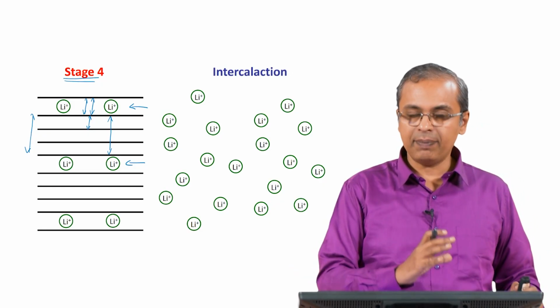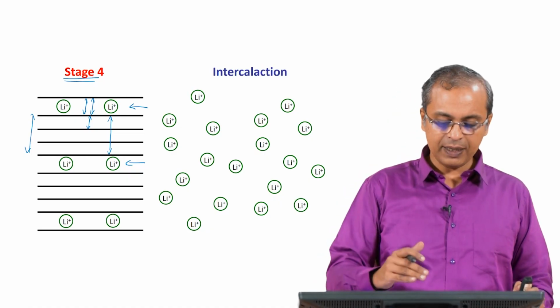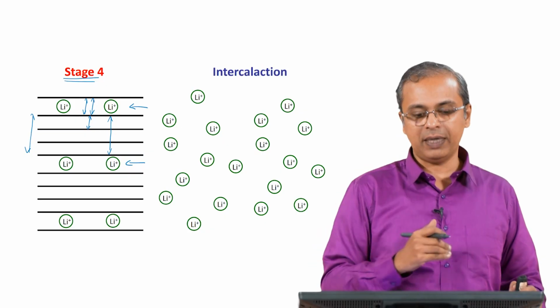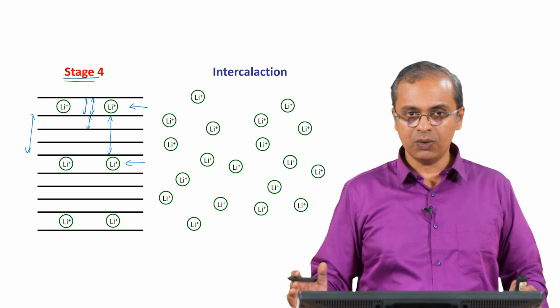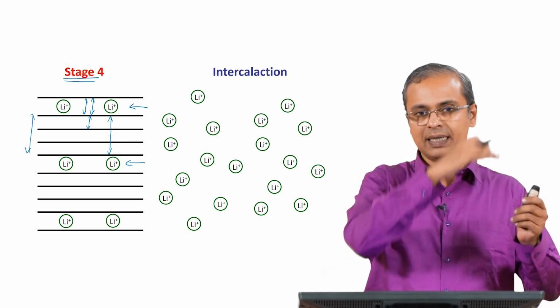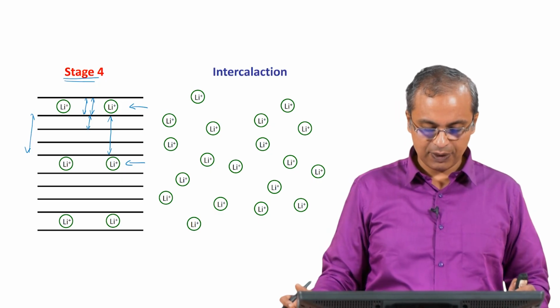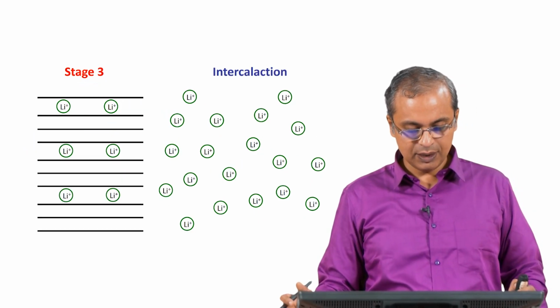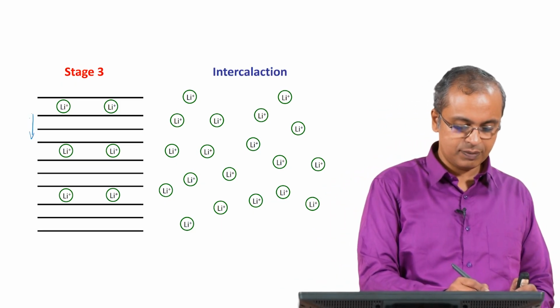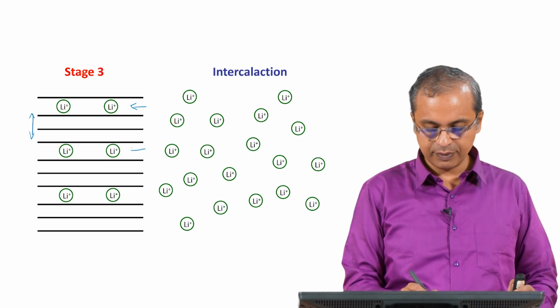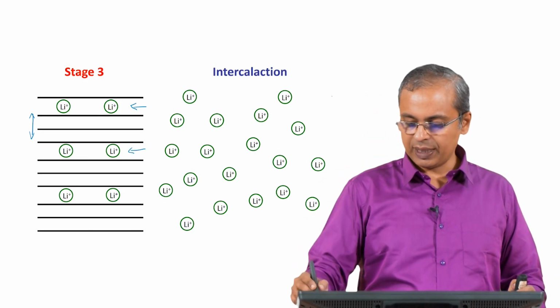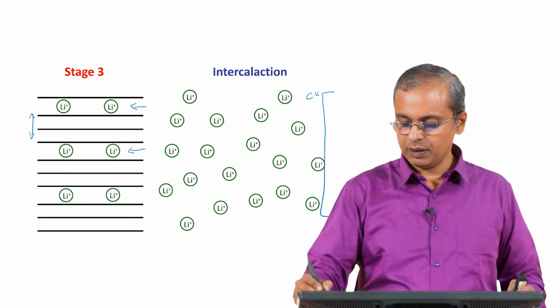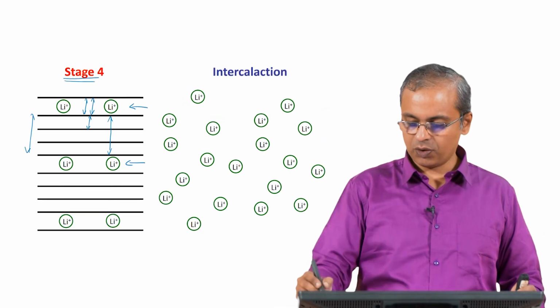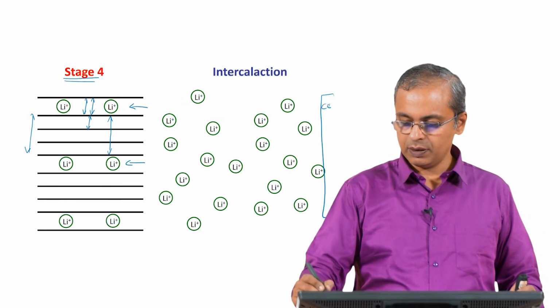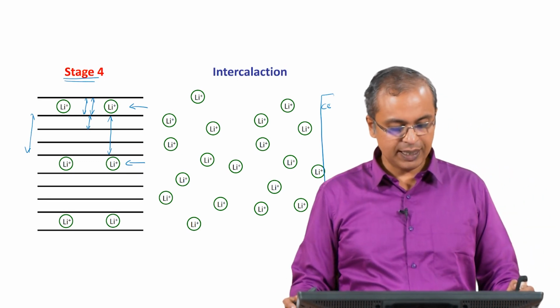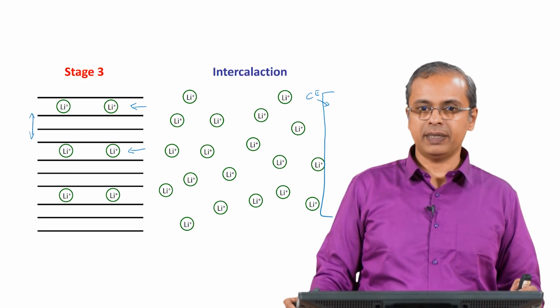Stage 3, as you can imagine with respect to this description, would be a situation where we have brought in so much lithium that on average there are 3 graphene layers between 2 lithium layers. So now you have 4 graphene layers between 2 lithium layers, you introduce more lithium, as they go inside and inside, they will readjust such that you have 3 graphene layers between 2 lithium layers. So this situation evolves into this situation. So suddenly you now have 3 layers only between every 2 adjacent lithium layers. Again the electrolyte is continuing to change here, and you continue to have a counter electrode here from where this is happening. So this is 4 layers of graphene between 2 lithium layers, this is 3 layers of graphene between 2 lithium layers. So this is stage 3.